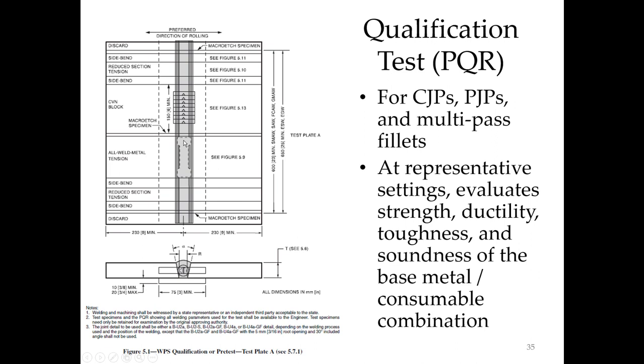What you'll see in these specimens is that primarily what we're testing is the weld metal. These tests do a good job of providing a weld metal test. They don't necessarily reflect how that weld metal will combine with the joint to be used. The dilution that you get from a real joint would be different. The dilution being the amount of base metal in the joint. But the code sets up the test like this because the thinking behind the code is that we really want to be sure we have good weld metal.